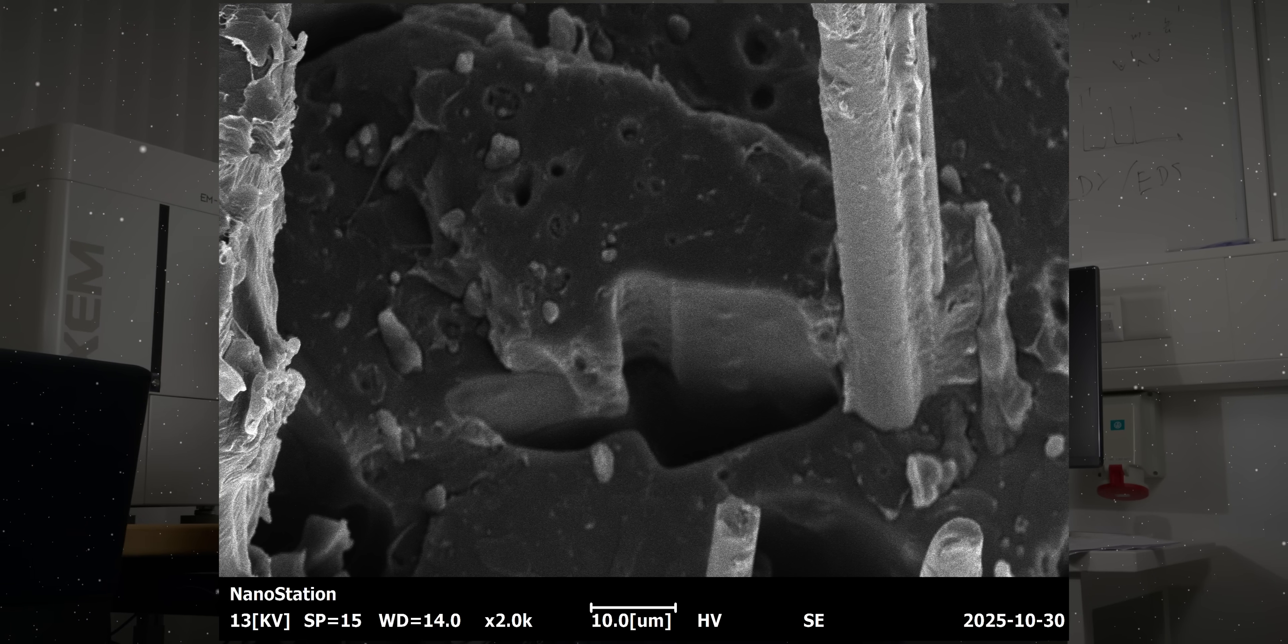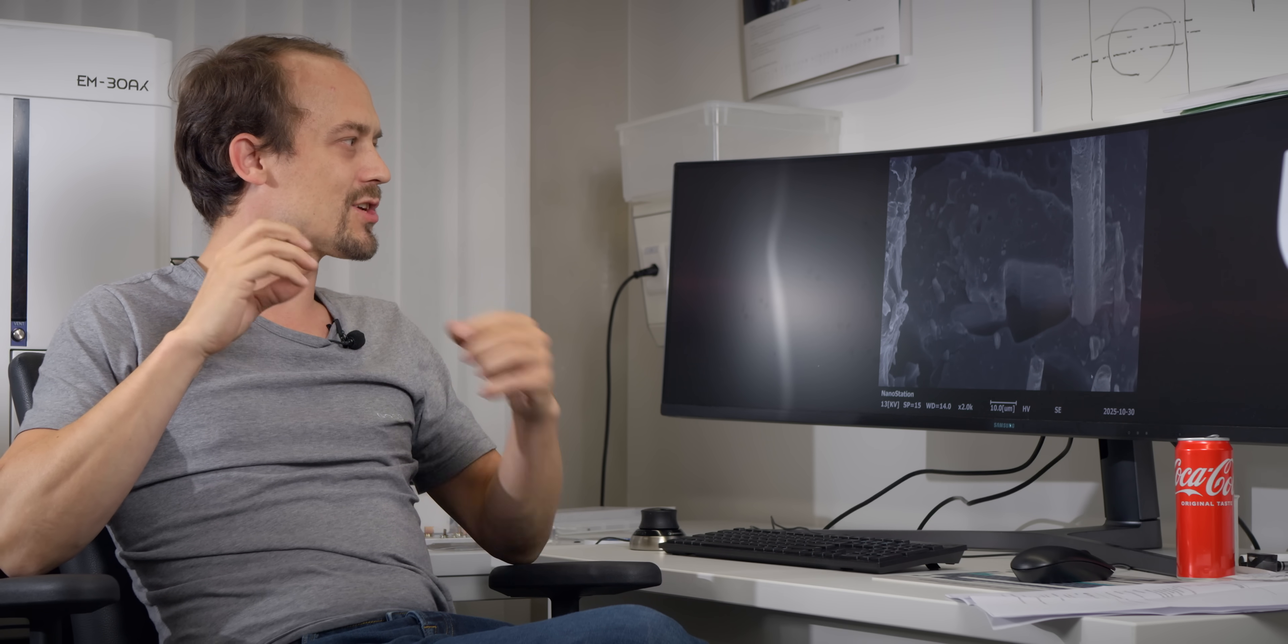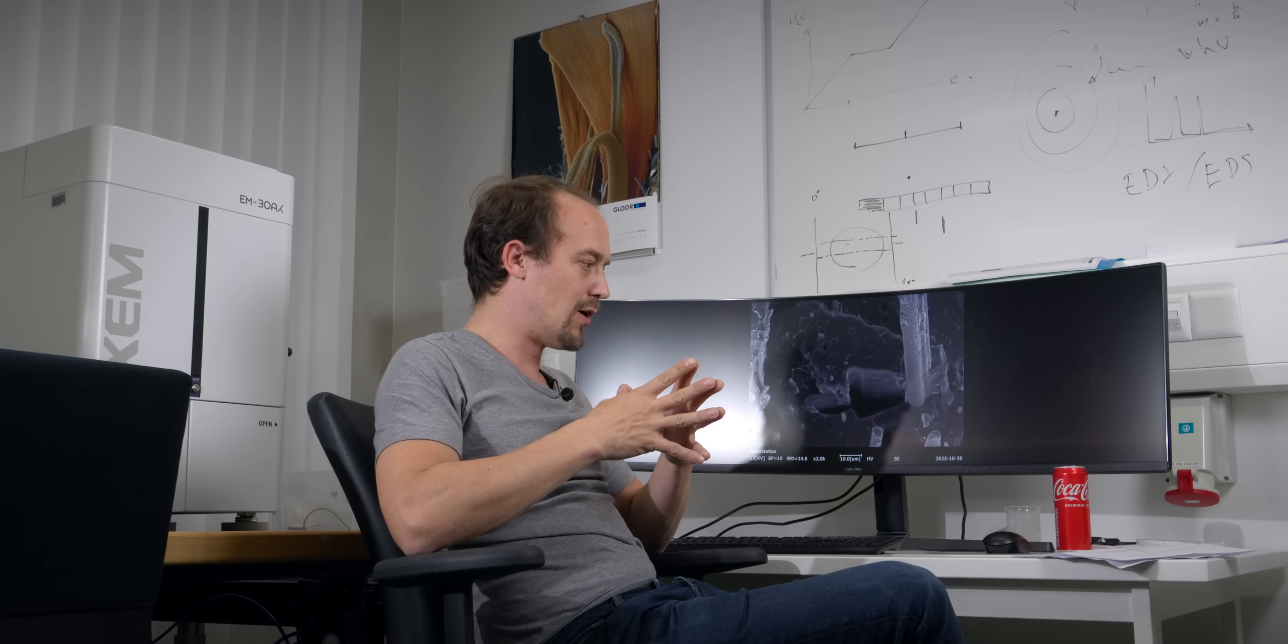As you can see, that's about 30 micrometers of an air bubble. That's a 2K image, like 2,000 times magnification. So that was interesting, and I actually wasn't sure if that is maybe an artifact from me breaking it while frozen or even from freezing itself. So what we will do next, and what I haven't done yet, is micro CT imaging to look into an undisturbed part.